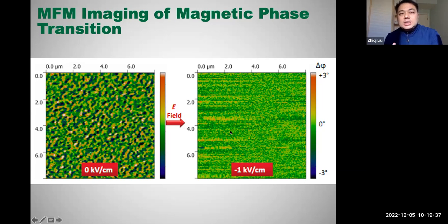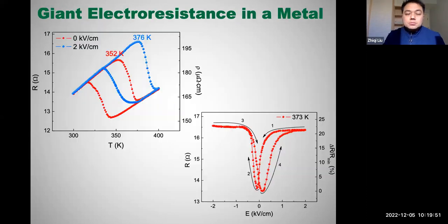This suggests that a small piezoelectric strain could be very useful for tuning the magnetic phase of iron-rhodium, especially around its phase transition temperatures. And if we look at the transport curves, the resistance as a function of temperature, which could easily give you the phase transition temperature, for example, this sharp drop, and also the two sharp drops in resistivities correspond to the metal magnetic transition temperatures.